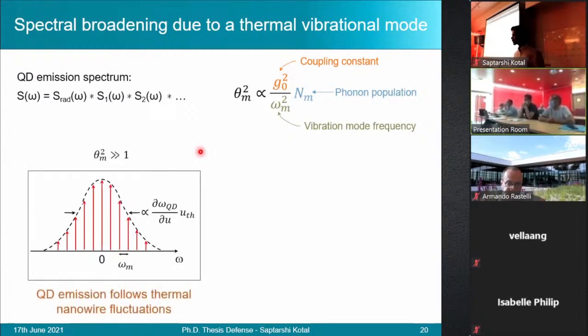Now, two regimes can be identified as a function of theta m squared. First, we consider when theta m squared is greater than 1. In this case, we observe that the spectrum is predominantly composed of a comb of spectral lines, which has a Gaussian line shape.